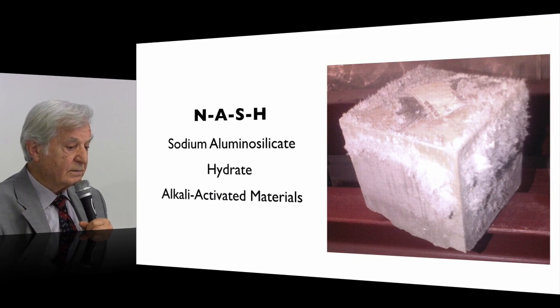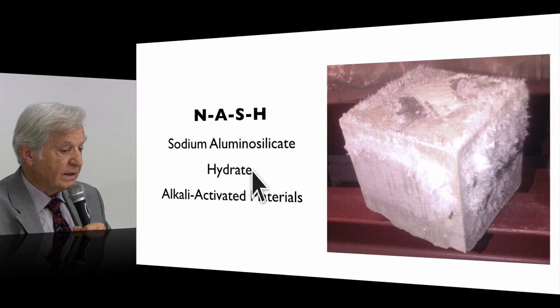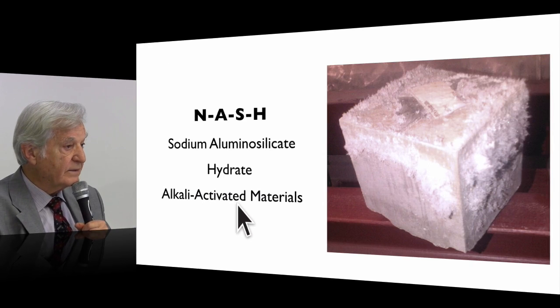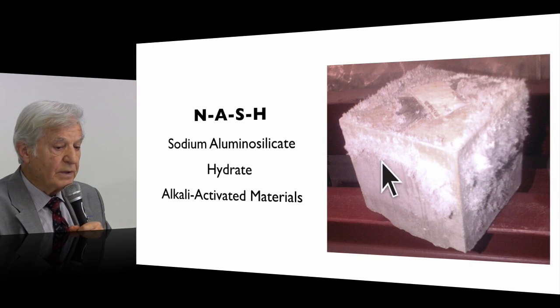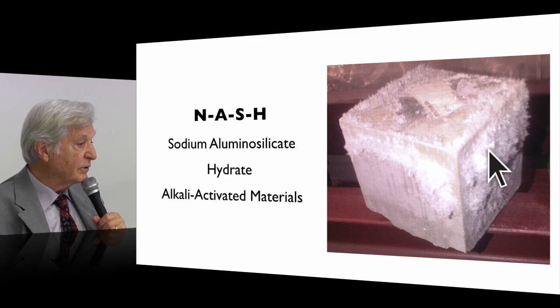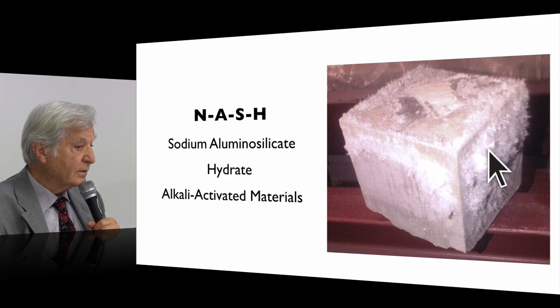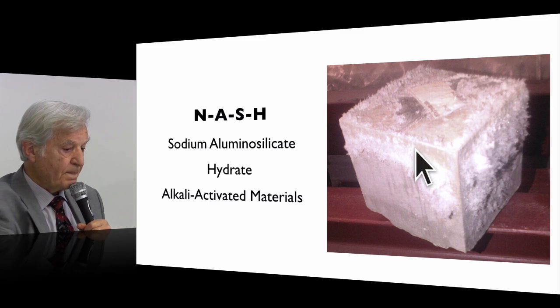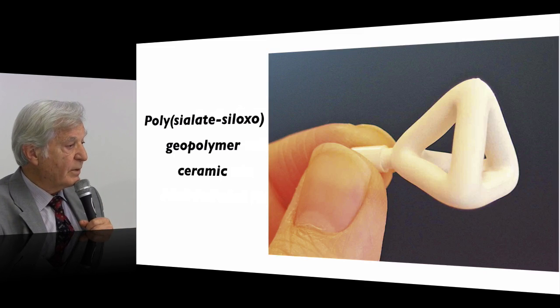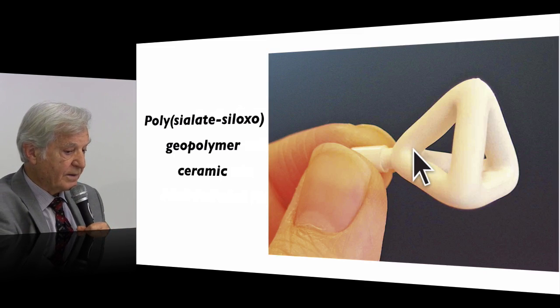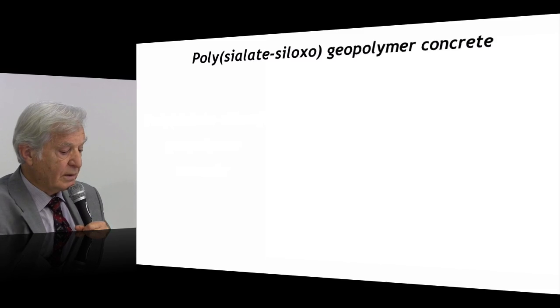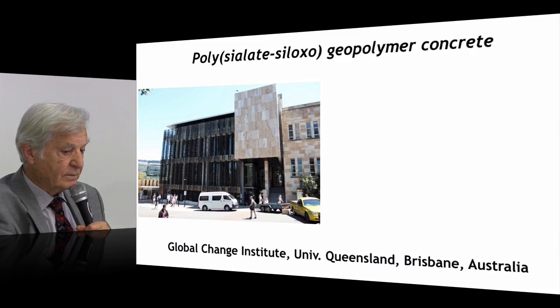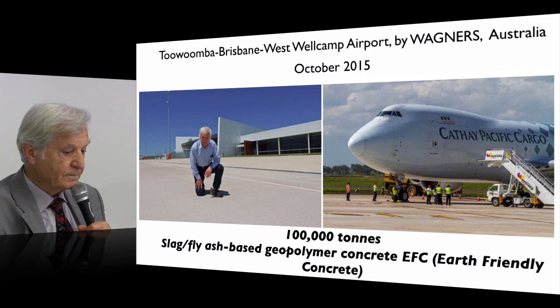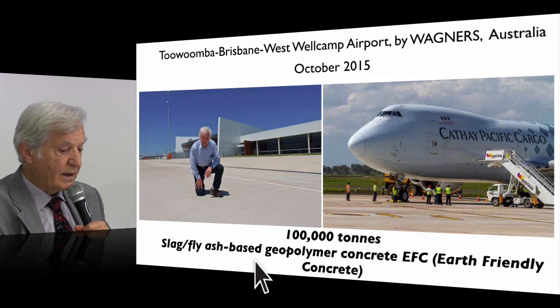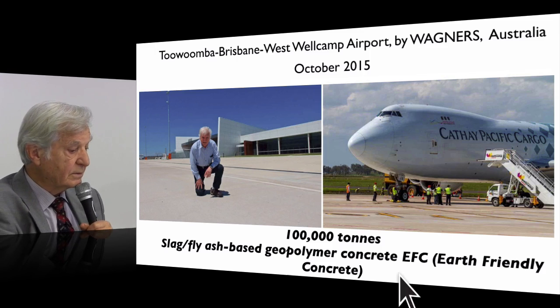This is NASH, sodium aluminosilicate hydrate, alkali activated materials, with all blooming, all the sodium coming out. This is a wrong mix. This is geopolymer ceramic. This is geopolymer concrete. This is slag fly ash based geopolymer concrete.